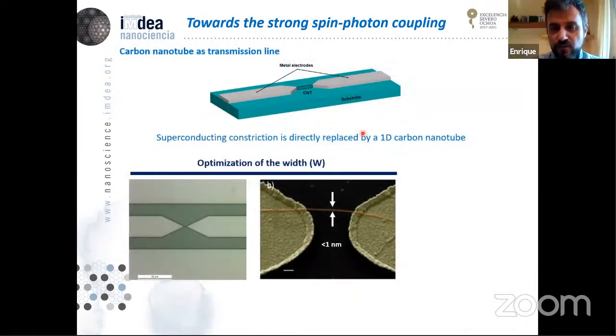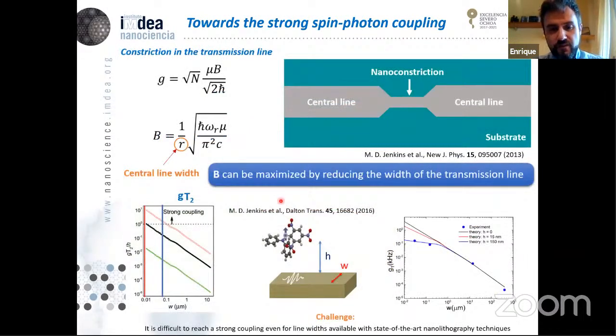So what we are actually trying to do now in my lab at IMDEA is to go to even smaller scales and try to replace part of the transmission line by a single carbon nanotube. So we literally cut the transmission line at a specific position and we deposit a carbon nanotube. The carbon nanotube by itself is already extremely narrow. So in the end, it is a 1D material. We can have carbon nanotubes that are around 1 nanometer, so we would be really on the left, on this limit part here of the graph.